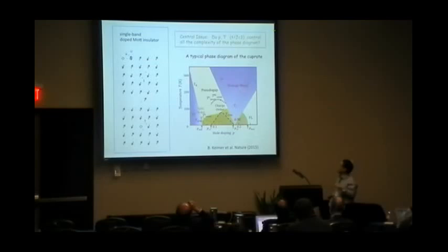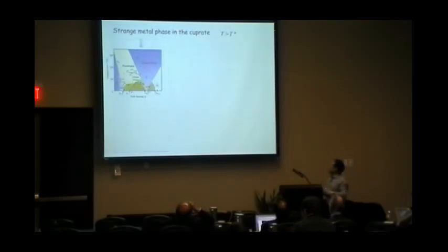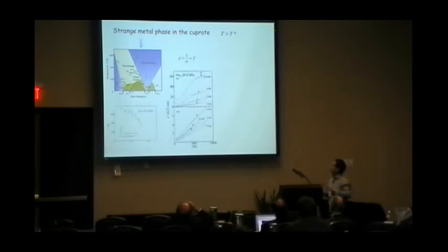which is actually the strange metal, where the temperature is increased high enough that all long-range orders are melted by thermalization at high temperature. And therefore, this should be one of the purest cases in which to look at what the exotic physics is. So here, the strange metal, let me say a few words. It's characterized by two things. One is that the resistivity is linear in temperature, with no upper bound up to 1000 Kelvin. You still see a linear T, and then the resistivity deviates from linear T at the so-called T-star here, which has a strong doping dependence.